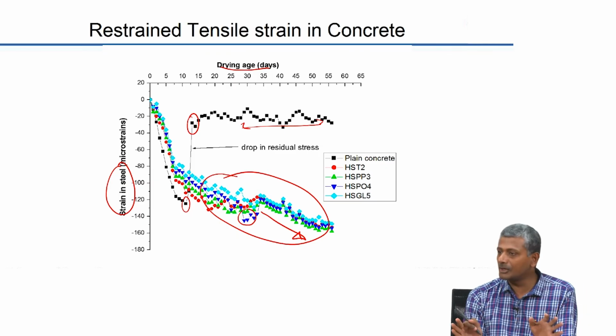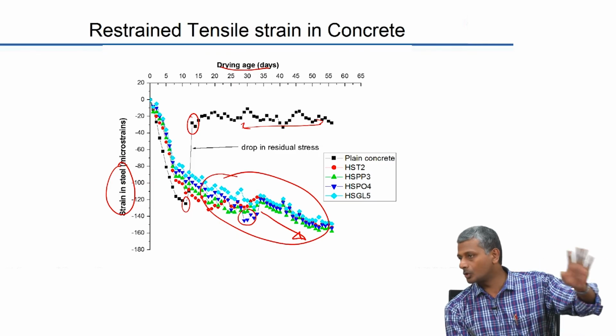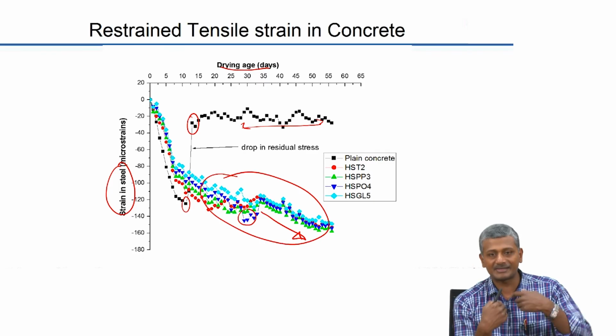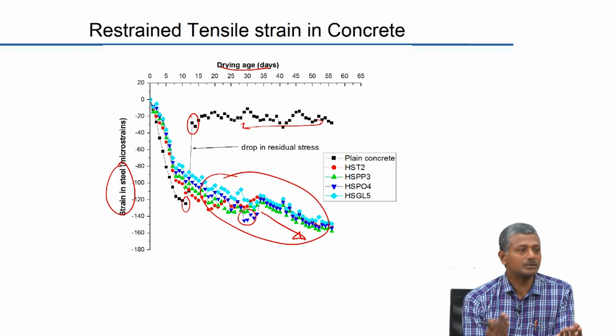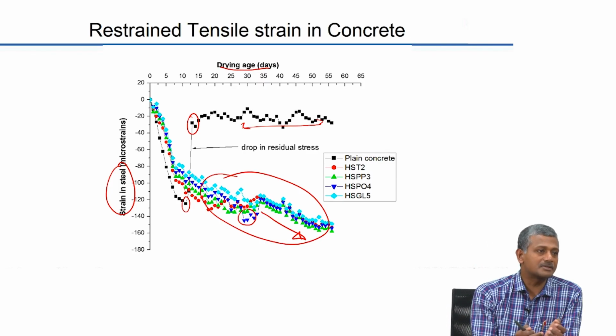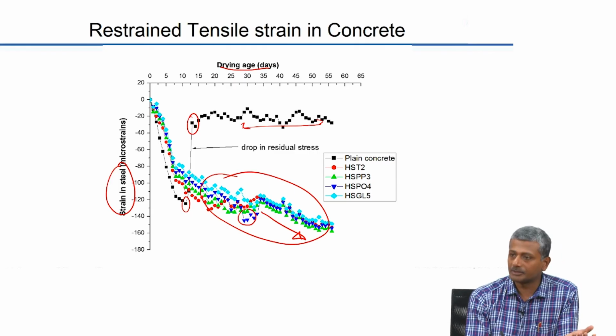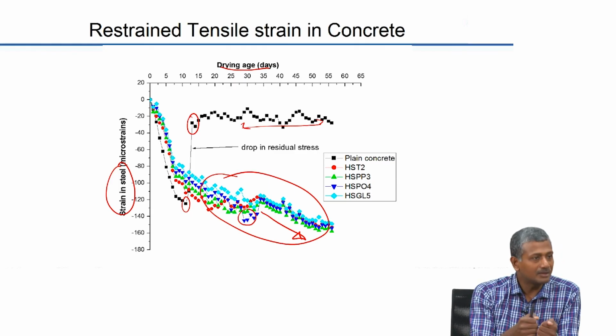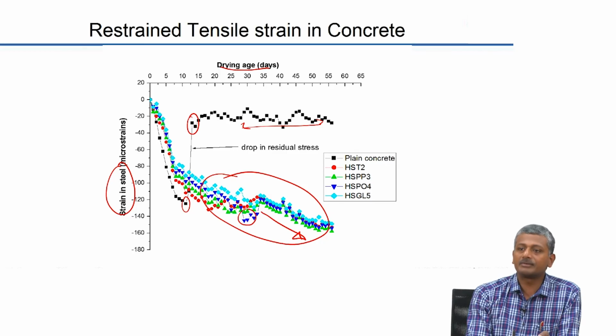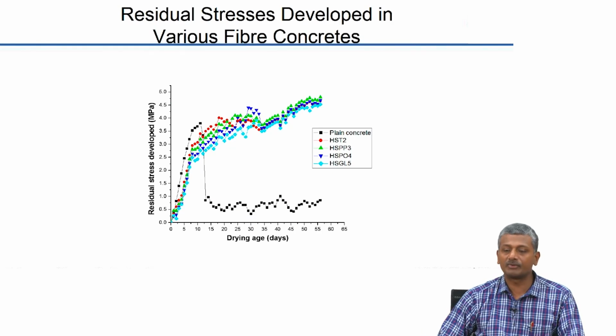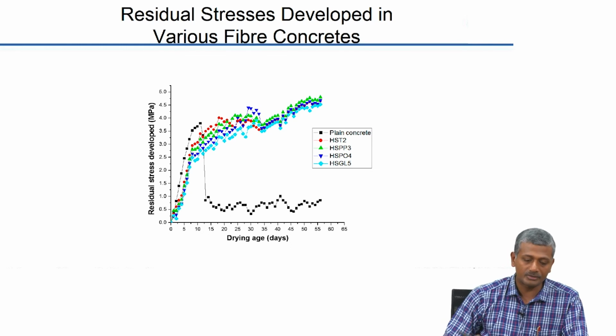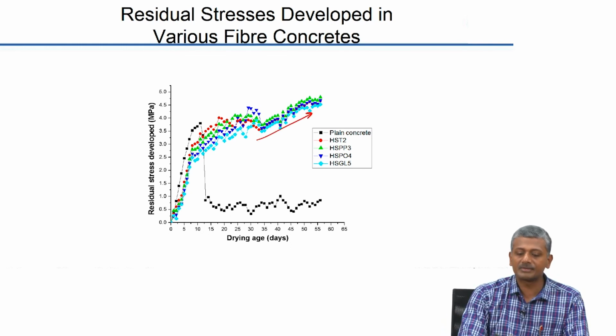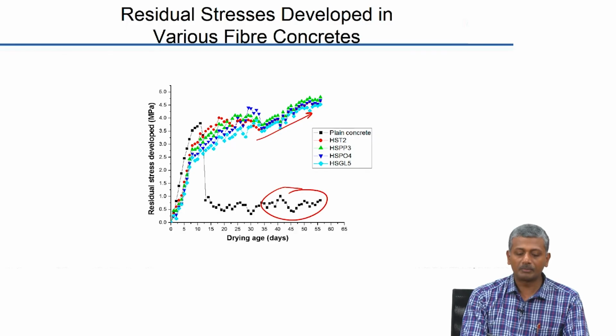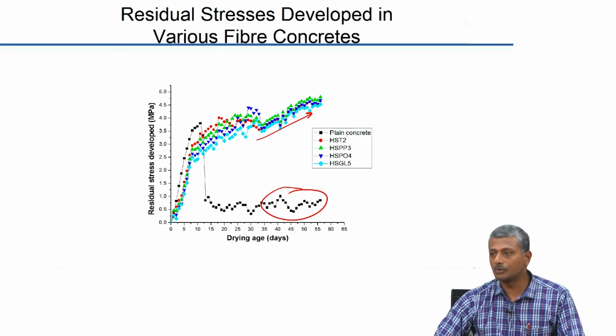So, concrete is continuing to shrink at the same rate. The control concrete and fiber reinforced concrete has the same ability to shrink. It is only the fact that once the cracking appears, the stress is now transferred to the fiber, because of which it can continue to shrink without resulting in a significantly large amount of cracking. Again, this is the development of residual stresses in various fiber concretes. So, with the fiber concretes, the stress continues to develop. With the plain concrete, your stress is almost down to 0.